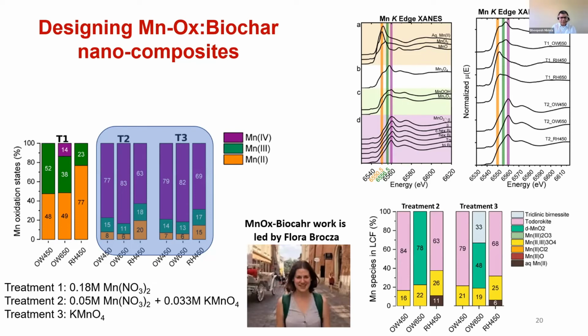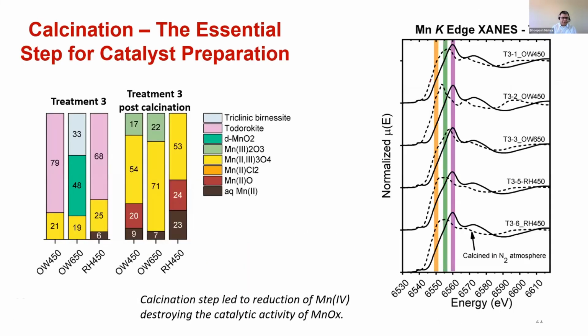So we were like, okay, great. At least we have manganese 4 oxide, and particularly if you look at OW650, we had MnO2, we had triclinic birnessite. And so that was very encouraging, that okay, that could be a really good one. So now, as you know, calcination is an essential step that most of us want to do for making good catalyst. We did calcine this material, and what we saw was pretty interesting and remarkable in its own way.